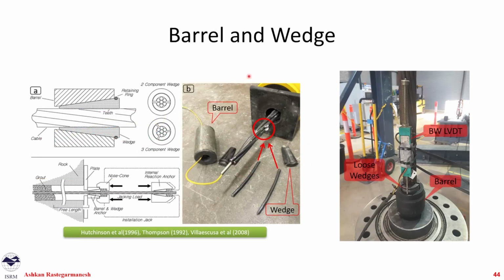We studied the barrel and wedge. If you remember, we mentioned it in the beginning. The way we studied that was that we put a dedicated LVDT on top of our cables, which was tied to the cable and resting on the barrel. And we wanted to see the movement of the barrel relative to these wedges during the pull-out test, to basically see how much energy is lost or how much movement is lost.